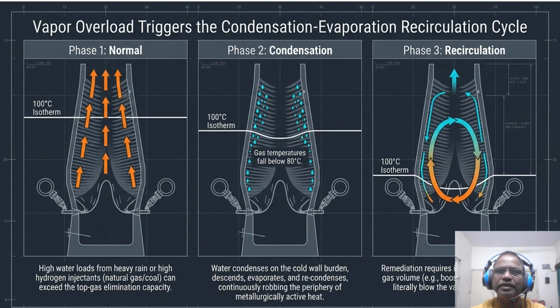Now look at phase 3. That water evaporates in the hotter zone below and recondenses at the top. This creates a vapor loop indicated by circular arrows, which continuously robs the periphery of metallurgically active heat. To break this, you cannot just wait. You must increase the specific gas volume, often by boosting coal injection to literally blow the vapor out of the top and restore the thermal profile. If you don't, the periphery will eventually go stone cold. To see this happening in real time, we have to look deeper than just top gas averages.